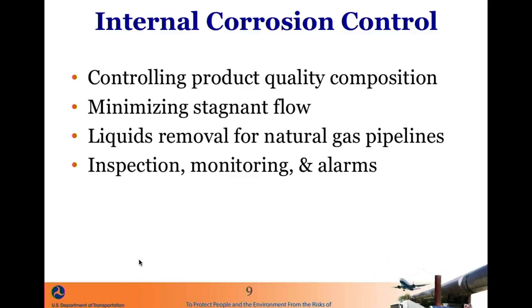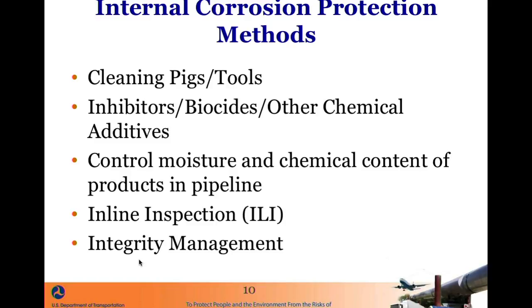So, coupons are placed in the pipeline. There's monitoring equipment to test for the amount of water, CO2, H2S, and there can be alarms that go off in the control room if they exceed certain levels. So, to remove water, cleaning pigs are often run to push water out of the system.